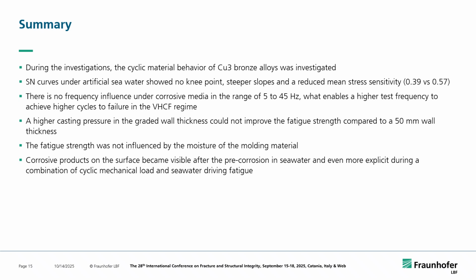At the end, we have some points where we say, okay, we have no knee point under corrosion. It's not surprising, but we had also no knee point for the alternating loading tests under ambient air, which was a bit more surprising. We have a slightly reduced mean stress sensitivity under corrosion. And we made the fatigue tests at 15 Hertz. This was the basis, but we also tried to see what happens at 5 and 45, and there we can state that nothing happens in the elongation or shortening of the lifetime of the specimen.